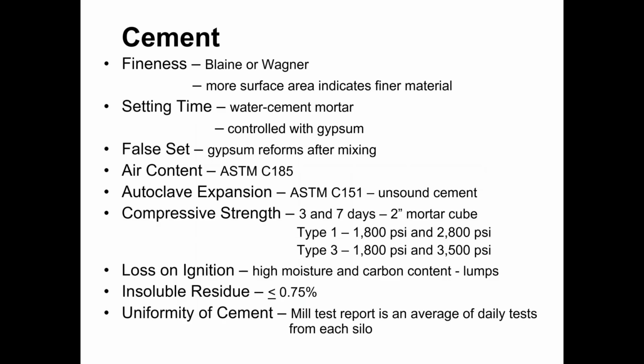All right, the setting time shown on the mill report is intended to provide relative information. Relative meaning that you could take one cement mill report and compare it to another mill report, and based on the set time that's reported, you can make certain assumptions as to how that cement would perform in your mix design. It does not give you the set time for your mix design. Water cement ratio will affect set time. The other proportions of other materials in the mix design will affect set time. So the set time reported on the cement mill report is not intended to give you the set time for your concrete mix design. Instead, it's relative information that will help you compare multiple cement samples.